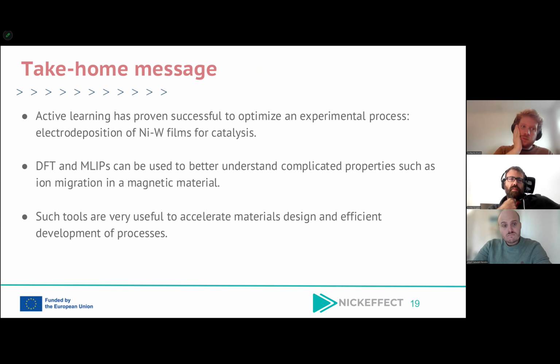So this takes me to my take-home message. So first, active learning has indeed proven useful and successful to optimize an experimental process. So it's not only materials design, but also how to deposit and actually make these materials. So in this case, it was the nickel tungsten films that are used for catalysis.